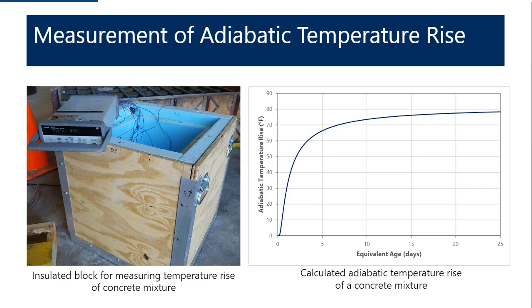So basically what that means is if you have a very large element, say a 12-foot thick element, you can expect the interior of that element to rise by about 80 degrees Fahrenheit. So now if you're thinking about trying to limit your total internal temperature to less than 160 degrees Fahrenheit, you're starting to think that this might be related to your placement temperature. If you have a 160 degree maximum, you're expecting 80 degrees temperature rise. You want to make sure that your placement temperatures are less than 80 degrees to stay under that limit.